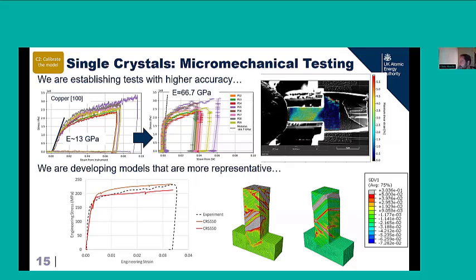this very miniature beam. So I don't know if it's possible to see, but the scale bar on that video is 5 microns. So these are very small tests, and we can map the strain evolution on the surface of the micropillar. And more importantly, we can correct then for all of the misalignments and compliance in the system to get accurate data from it.